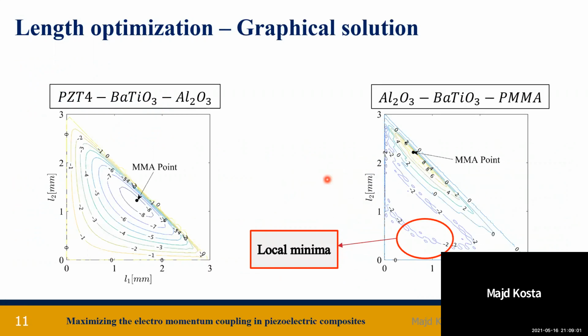We also addressed the same problem with a graphical solution. And we can see that the same optimal design with the same value has been obtained. And moreover, we can also see that in the second composition, the problem itself in its nature has several local minima, which might hinder the optimization process. And to overcome that, we evaluate the value of W at 20 random points. And once the optimal region is found, from that point, we apply the MMA method until the optimal design is obtained.